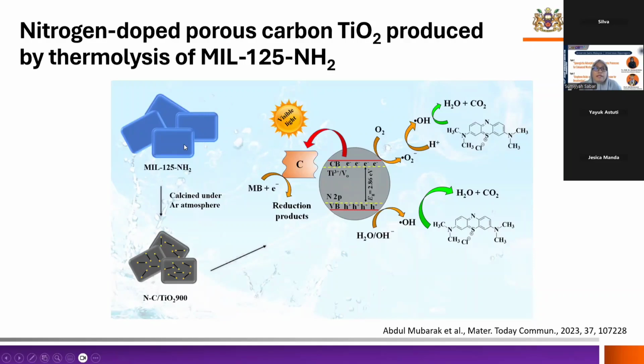Okay, so in this case, our aim is to use MOF to produce adsorbent, to produce photocatalysts that have a good adsorption ability. So in this case, what we did is that we produced thermolysis of this MOF under inert condition, where it produces nitrogen doped carbon porous titanium dioxide. Okay, so aminated MIL-125 is a Ti-based MOF. So under calcination, it will produce a titanium dioxide.